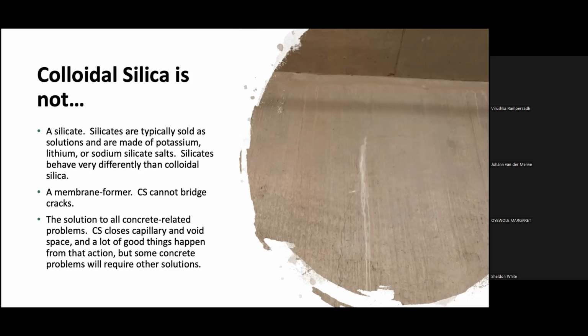So with colloidal silica on existing concrete applications, for instance, it's not going to bridge your cracks. You want to apply it first, allow it to coat the sidewalls of the crack to shut down that lateral water movement, and then come back with your injection material or other crack repair materials. It's not the solution to all concrete-related problems.